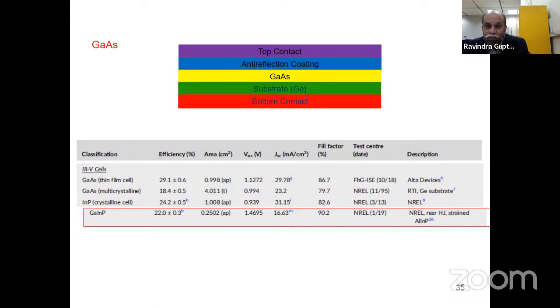But of course, thickness is very, very low, 10 nanometer. So it is good, but 10 nanometer fabrication means you need very sophisticated instruments for manufacturing. This is the problem. And gallium, Ga, this is another problem. It's not so plentiful, so it is an expensive material. That's why when we need it for space application, when we have very little space, when we need something very light, then we go for this solar cell. And you can see for thin film efficiency is very, very good, 29%. Of course, the area is very small. For the large scale, you can see 4%. Sorry, 18%. This is 4 centimeters square.